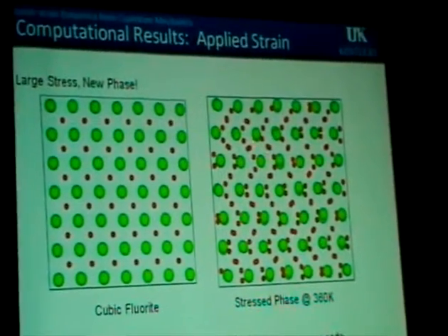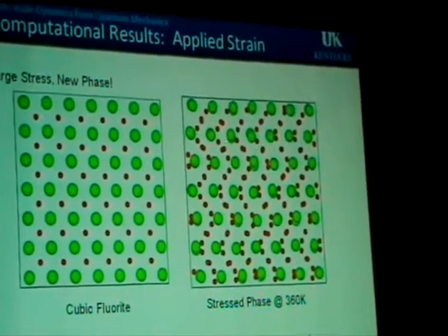What this actually amounts to is that you have layers of 4-fold coordinated and 3-fold coordinated oxygens. Where does that come from? You can go into the literature and there's a series of papers on amorphous zirconia, and they report the appearance of 7-fold coordinated zirconium atoms in amorphous zirconia. So that's where this 3- and 4-fold coordinated oxygen comes from. This was pretty cool, but it doesn't directly answer the question about diffusivity. That, of course, comes about when you heat things up.